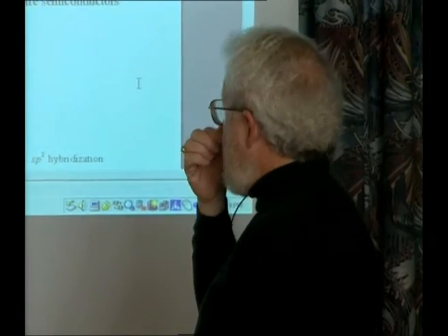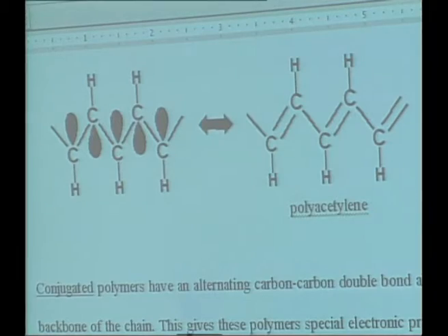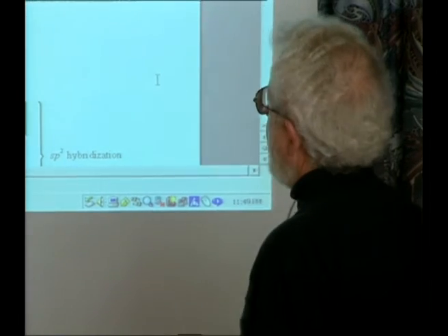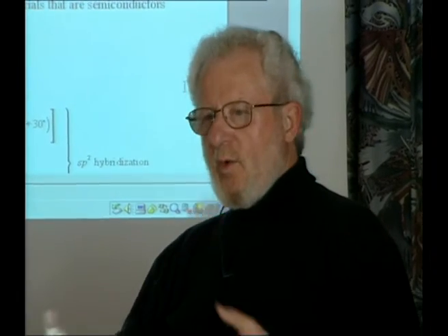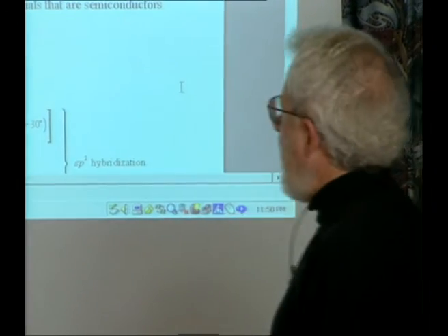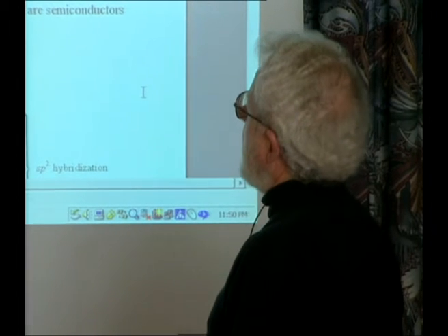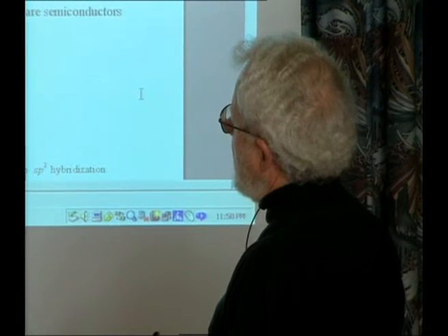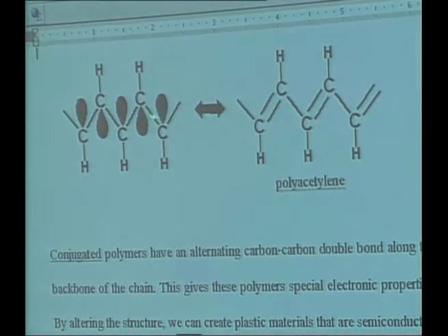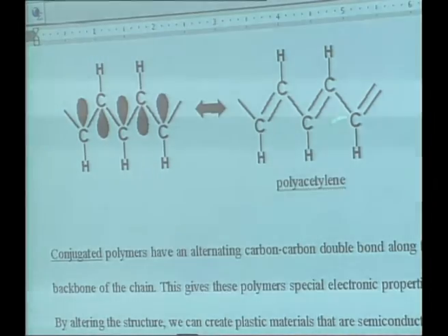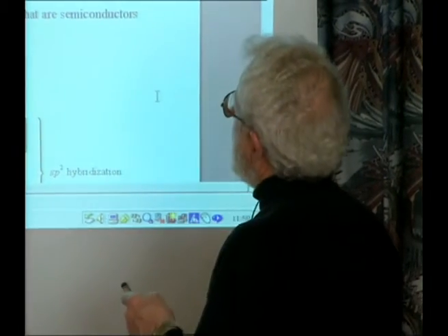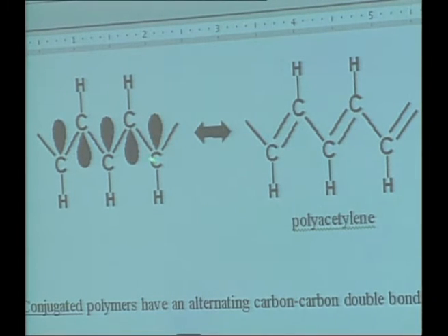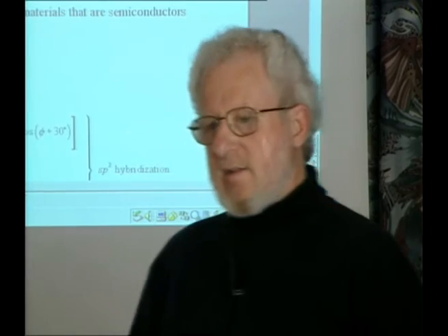But very quickly, if you start to do experiments, you conclude that's not the case. Assuming that the electron-electron interactions are not so strong, and we'll come back and talk about quantification of that, then there's of course another possibility, which is that these pi electrons might want to form a weak pi bond. This one, this pair, this pair. And that's what's being shown here. Okay. And what that means is, if there's a weak pi bond, then that means that this bond length will be shorter than this one. And you get a bond alternated structure. And indeed, that's what one finds if one studies polyacetylene.